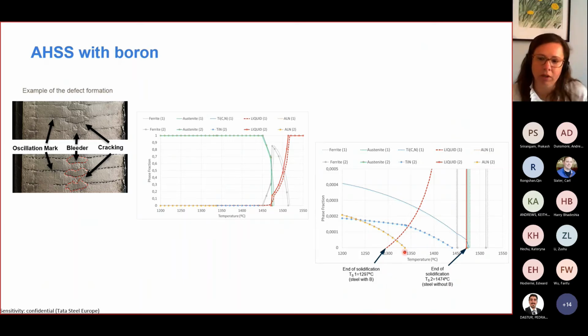However, be careful, because the amount of liquid at the last part is very little. You could say it's very little, so it's okay. In some cases it's okay, but in other cases you have to be careful, because this very little liquid phase present could be in between grains that are already solidified. Therefore, you could have cracking or even bleeding, like in the case of the photo, because those solidified grains are surrounded by a liquid film. Therefore, they do not have enough strength to hold, and they will bleed.